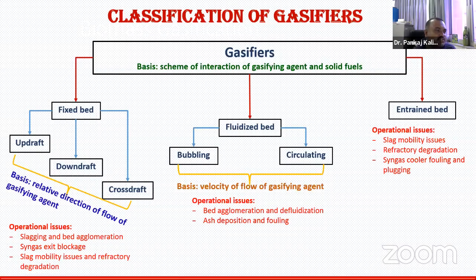There are operational issues in the case of fixed bed gasifiers, like slagging and bed agglomeration, syngas exit blockage, slag mobility issues, and refractory degradation. With time, the refractory degrades in this kind of arrangement. In the case of fluidized bed, bed agglomeration and defluidization are an issue, and ash deposition and fouling are among the major issues. In the case of entrained bed, which is very big in size, slag mobility is an issue, along with refractory degradation and syngas cooler fouling and plugging. This has to be addressed while making this kind of arrangement.